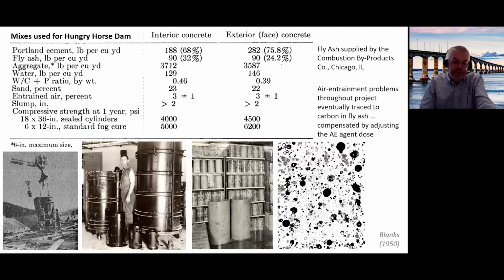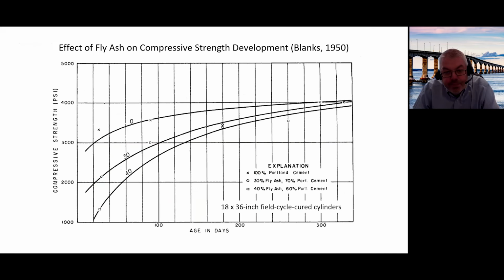I show these slides to my students because they complain about when they have to use 6-inch cylinders instead of 4-inch cylinders because of the increased weight. So I show them these slides to show some of the cylinders that were used back in the day with mass concrete structure. I mean, this was 6-inch aggregate, so you can't really use a 6-inch cylinder.